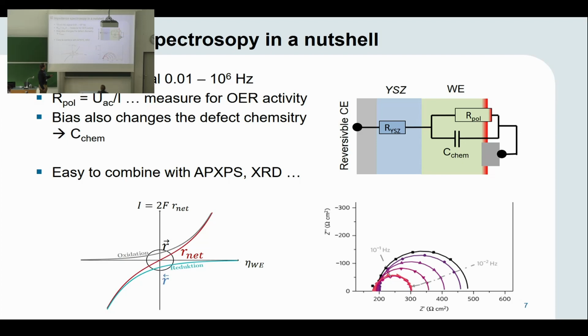And then we can fit our data in many cases with such a relatively simple equivalent circuit, which consists of an electrolyte resistance, which is of ohmic nature, the polarization resistance as a measure for the oxygen exchange activity, and the chemical capacitance as a fingerprint for the defect chemical state. And then we get some semicircular curves in the complex impedance plane from which we interpret our electrochemical results.